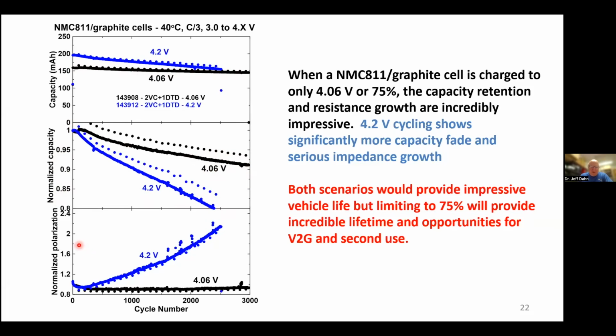What's really also interesting is we plot here what's called the normalized polarization. This is very similar to the battery internal resistance, which controls the power capability of the battery. And when you're charging to 75%, this internal resistance doesn't increase at all. So it means the power capability of your vehicle will not be compromised as it ages. Whereas when you're going to 100%, you can see the internal resistance has about doubled over this period of time.